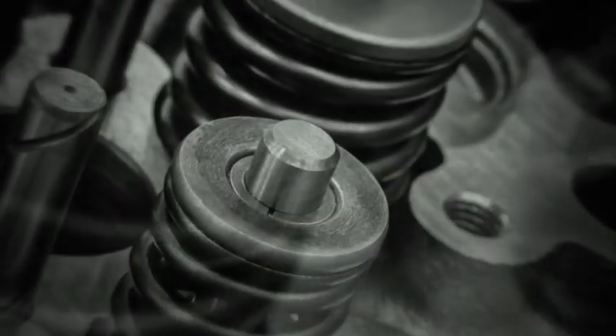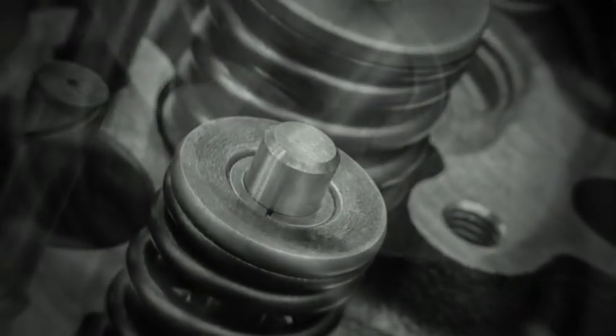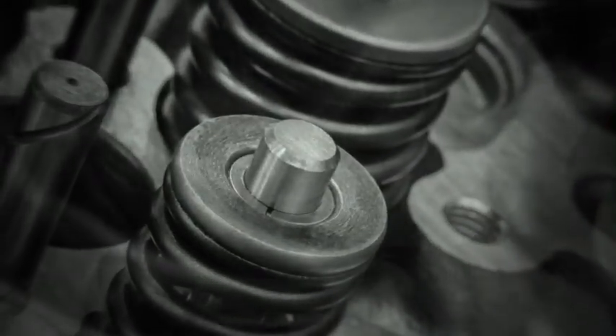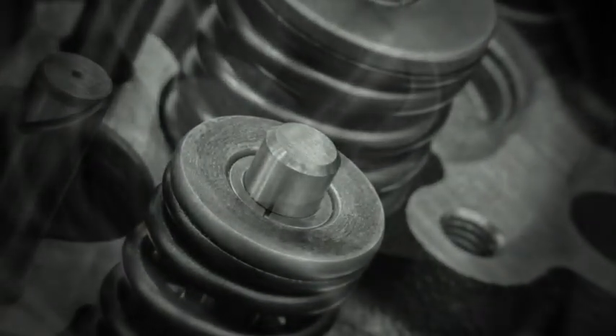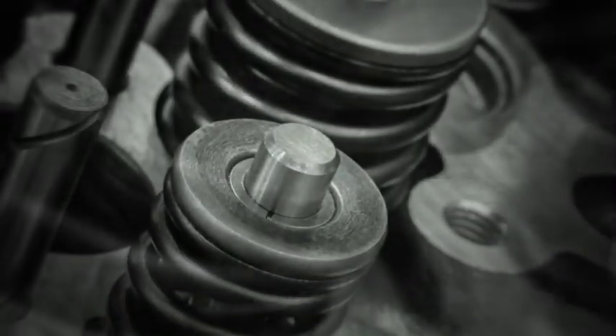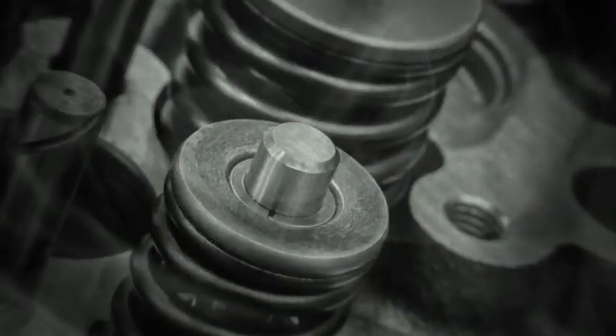The fracture surface and the shape left behind often reveal which limit was crossed. A spring that has taken a permanent set usually experiences stress, temperature, or time beyond its ability to recover. The coils may remain intact, but the free length changes. A vehicle sits lower. A valve spring produces less installed force. A seal face receives less pressure.